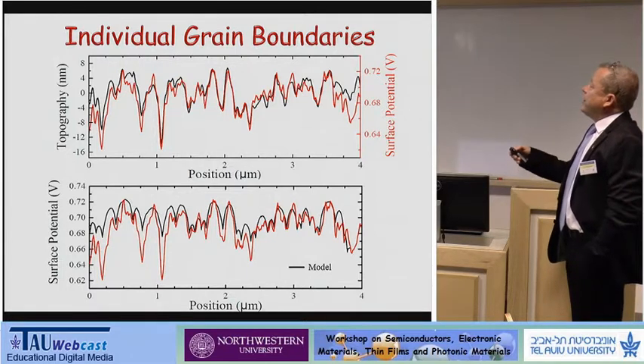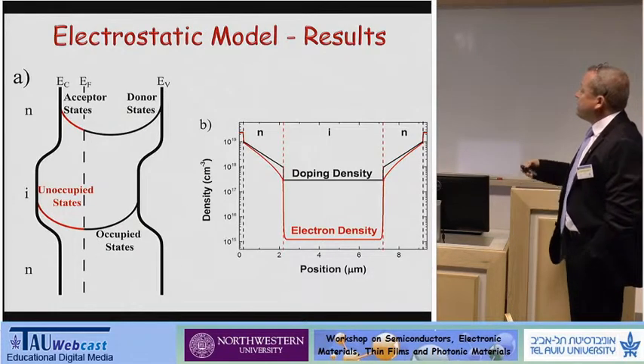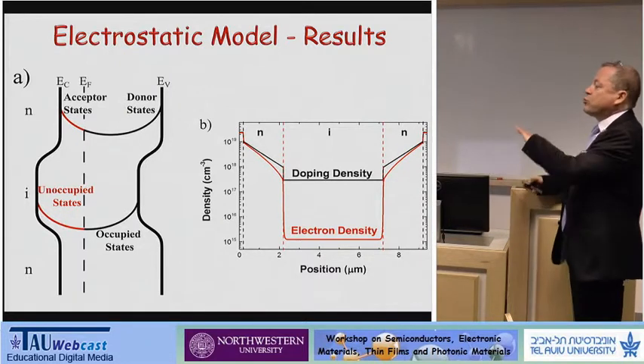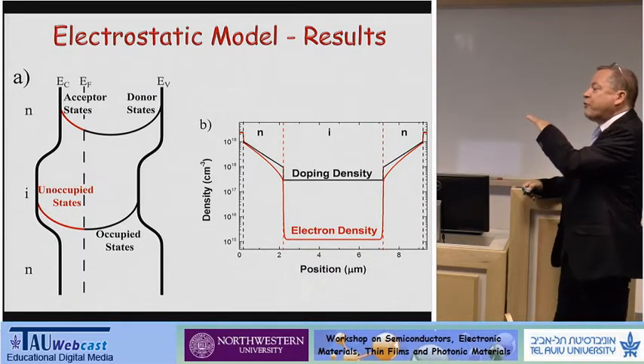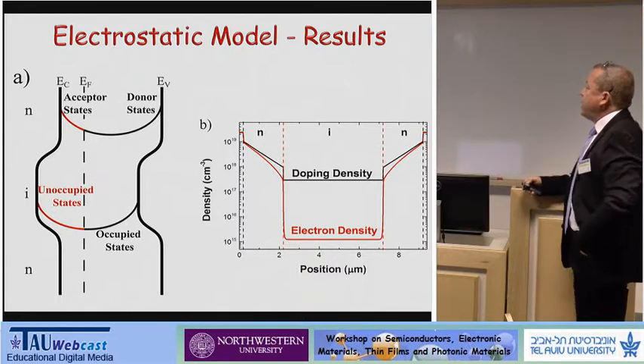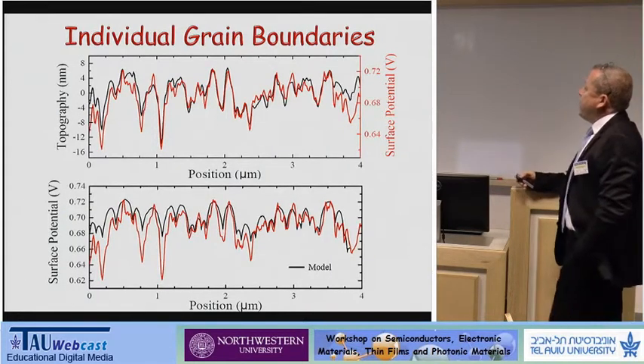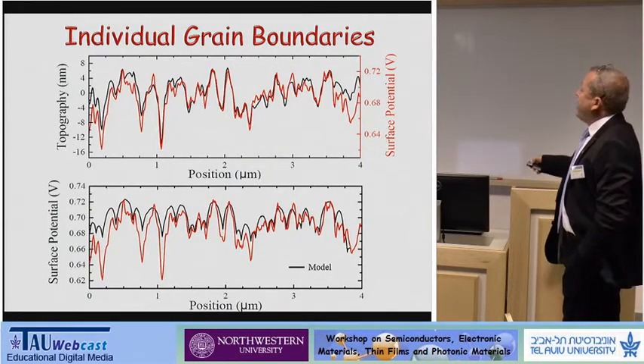So after this study, we went further on, and with a master's student called Asaf Shamir, we wanted to measure the individual grain boundaries. I didn't emphasize, but this study was based on the macroscopic or average Kelvin probe measurement. And here we went one step further and measured the potential profile along the grain.